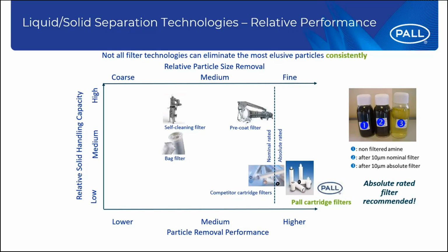That is very important, and it's illustrated in the picture on the right side, where we can see a non-filtered sample was submitted to two filters. One was a 10 micron nominal, and the result is picture number 2. And one was an absolute rated filter, effluent sample number 3. Directly, visually, you can see the performance of filtration. So a 10 micron from A is not equal to a 10 micron from B. This is very important to note.